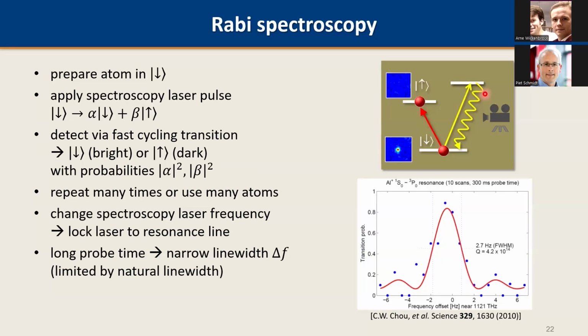Sorry, I had a question on the Rabi spectroscopy. Why does the transition probability peak not occur exactly at 0 here? Oh, that's because we drew the scale. Okay. And also, can you tell me about that 300 millisecond probe time? What does that mean exactly? That means that the Rabi pulse was 300 milliseconds long, with which we tried to generate that superposition. And of course, we have to dial in the correct laser power to power broaden the transition, so that the 300 millisecond pulse on resonance gives you maximum excitation probability.